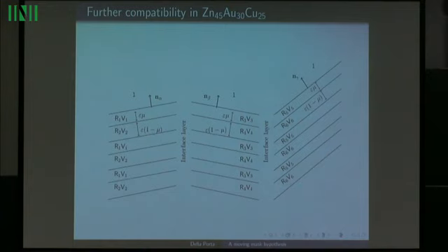We can mix different types of these laminates together and produce even more complex microstructures. And here, let me mention that n alpha, n beta, and n gamma do not lie in the same plane. So one can also construct three-dimensionally curved interfaces which evolve and at the same time satisfy this differential constraint that I was telling you about.